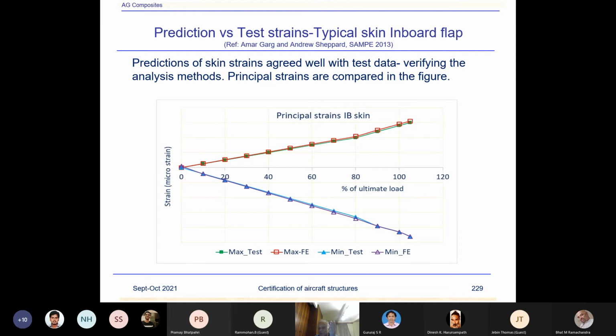Structures had to be reanalyzed because our AR, authorized representative of FAA, will not accept the results of the test and analysis until we had demonstrated agreement within plus minus 5% between the test and analysis, because the requirement is if you can't meet that, it means your analysis is not working fine. They don't have any confidence in the analysis method.